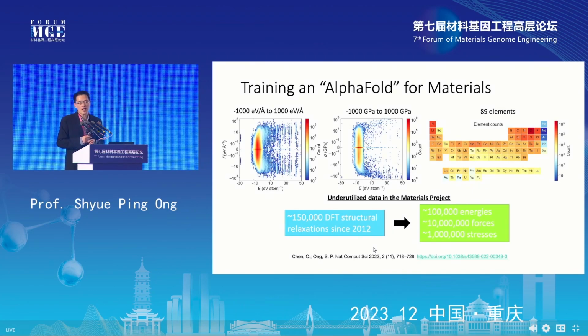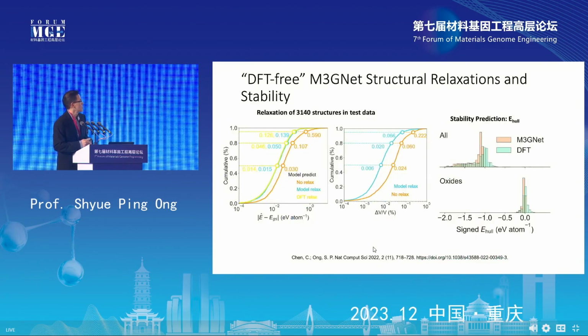So this is what we also call an AlphaFold for material science, right? So if you know, basically AlphaFold is this algorithm that was developed by Google DeepMind for predicting 3D protein structure, right? So here we develop a universal potential that can actually relax and get the structure for any material, okay? So just to show you that this universal potential actually works, okay, we can actually today get relaxed crystal structures that are within 1 to 5% of what you will actually get with DFT structural relaxations, okay? And this is almost near instant compared to DFT calculations.